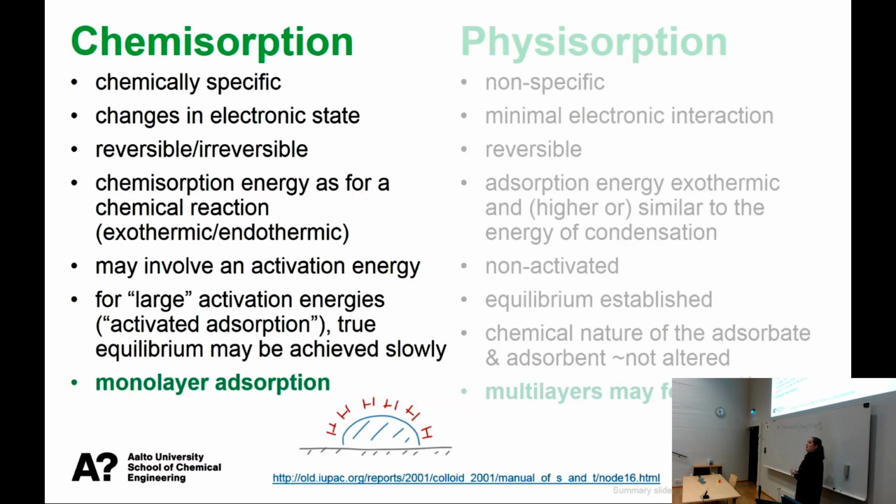So yeah, ALD, it's basically just chemisorption, and we have been talking about chemisorption in this course. We had a dedicated lecture to adsorption. So everything that has been said about chemisorption is valid for these individual ALD reactions. The last one here is in green, so monolayer adsorption. That's very important. That is the one that terminates the reaction. We are not going above a monolayer by definition.